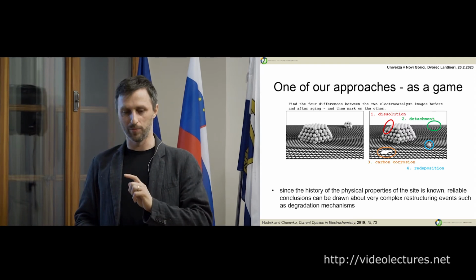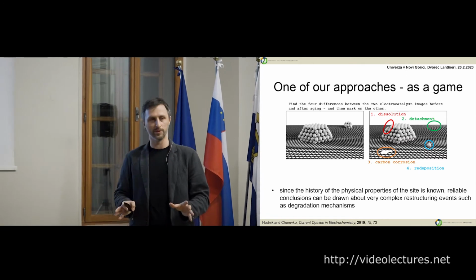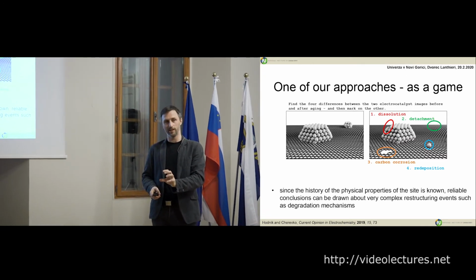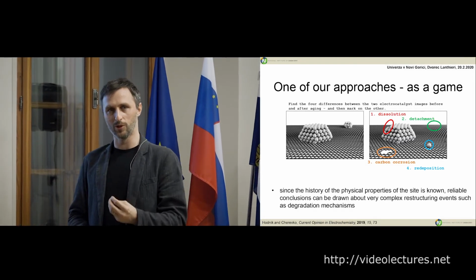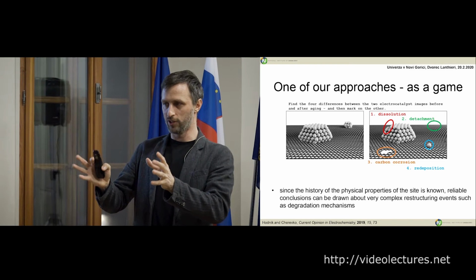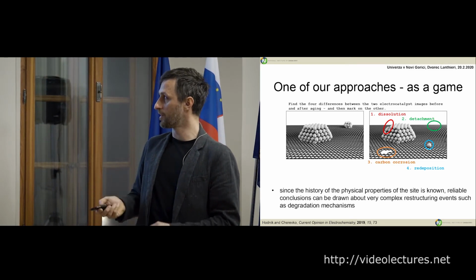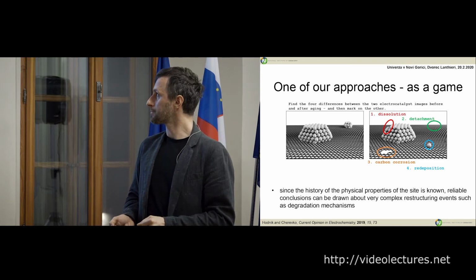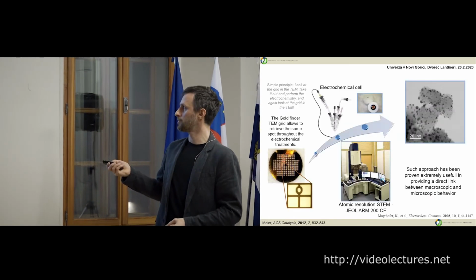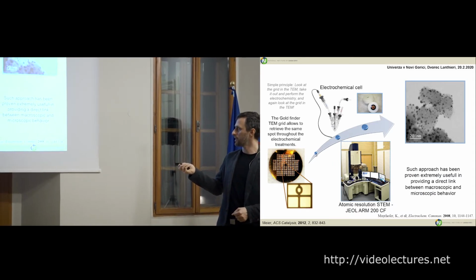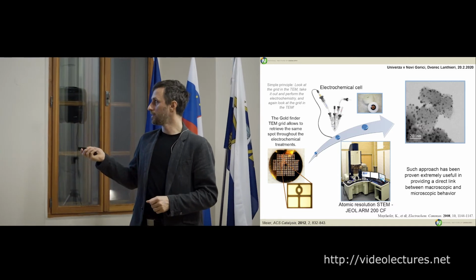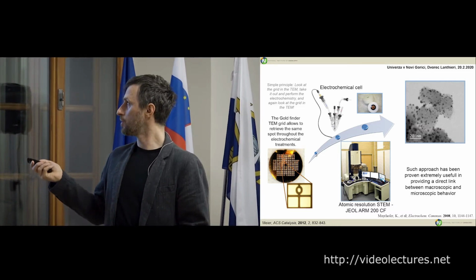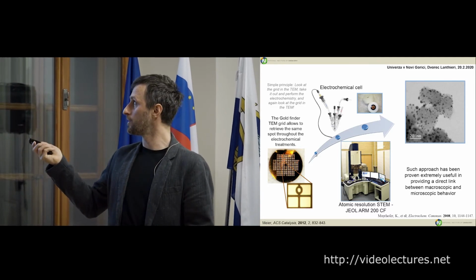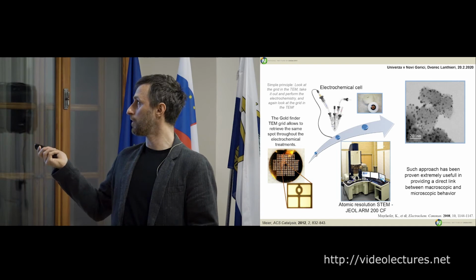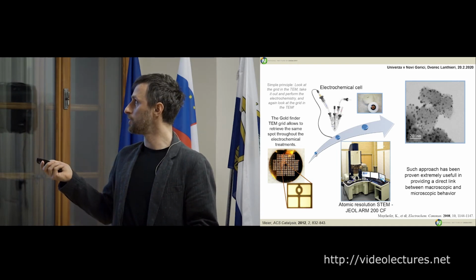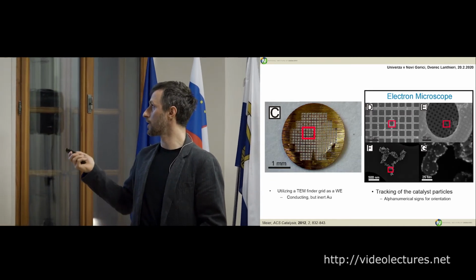This is important because in other random microscopy, you never are sure if this particle was already like this or not, and you don't know what happened to this particle. You can have statistical knowledge, but if you really look at it, you can really say, okay, this is what happened. Now, how you do this in reality is you take these TEM grids, which have numbers inside. They are called finder grids. Because they're gold, they can be used as electrodes. So you take the first image, then put the grid in the electrochemical cell, you do the treatment, and then you find the same location. It's pretty straightforward, but it's a lot of work. So this is how you track the same location.